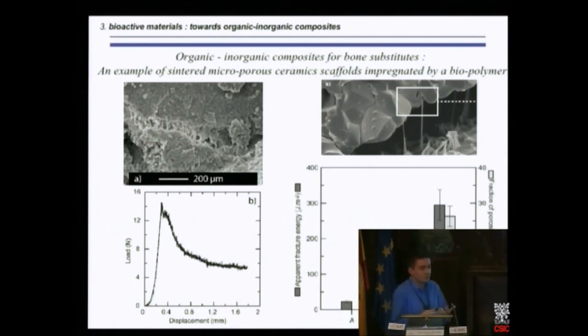And what are the results in terms of the energy to failure? What is the quantification of that? Here is the apparent fracture energy for different materials. So this is pure alumina. This is alumina impregnated with polymer with nanoparticles, impregnated once with a solution, and impregnated twice with an organic solution. So this is here pure ceramic, so very low apparent fracture energy. And here is the composite in which we have impregnated twice the ceramic with a polymer.